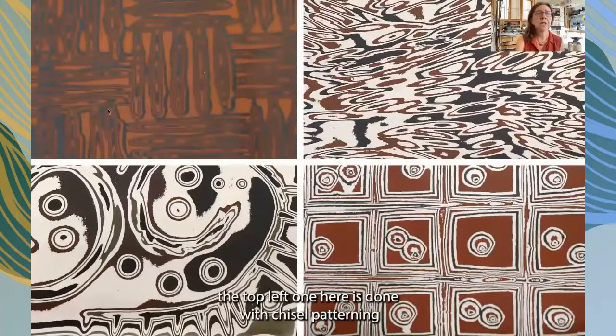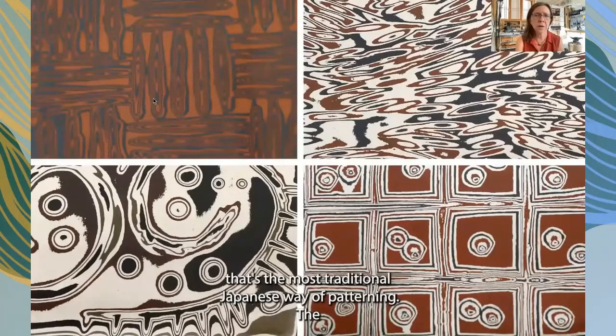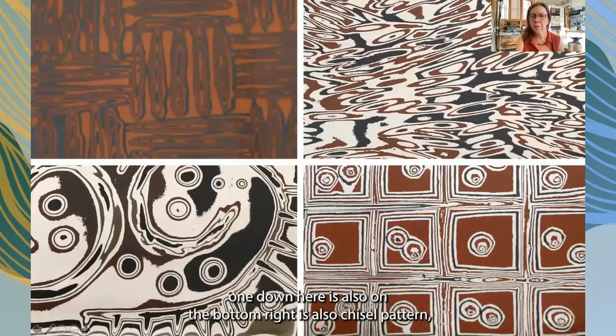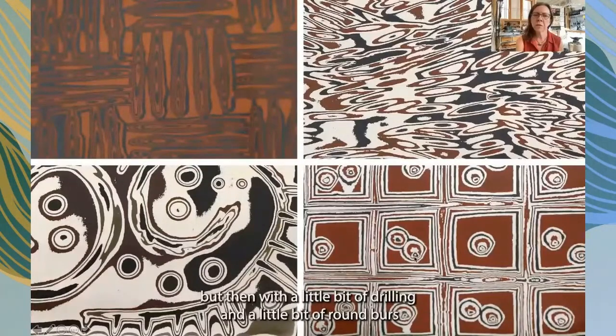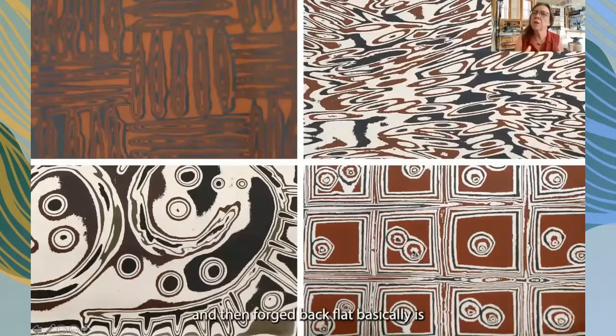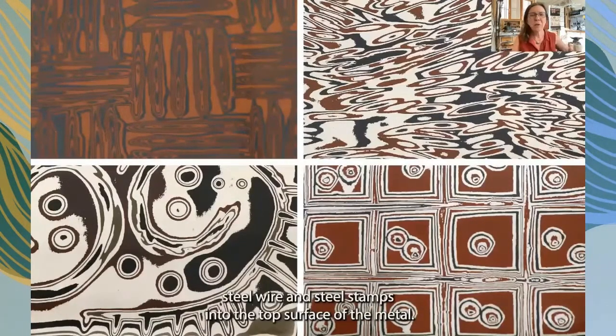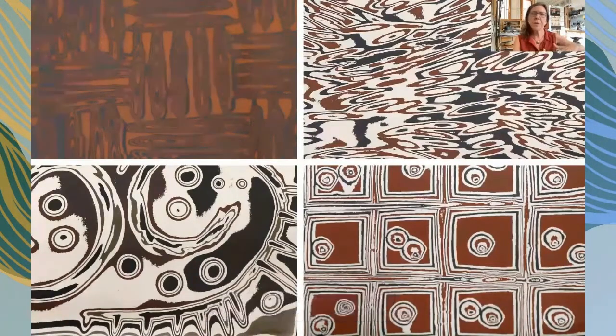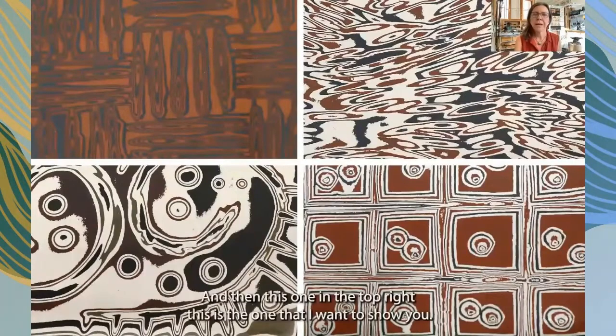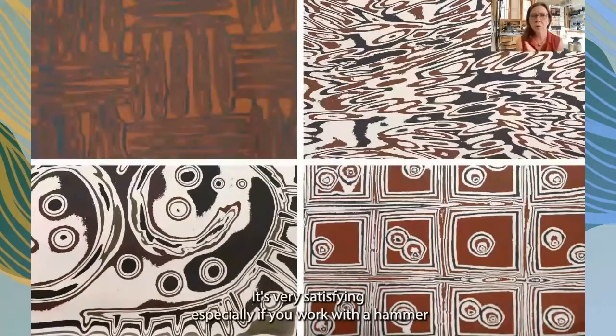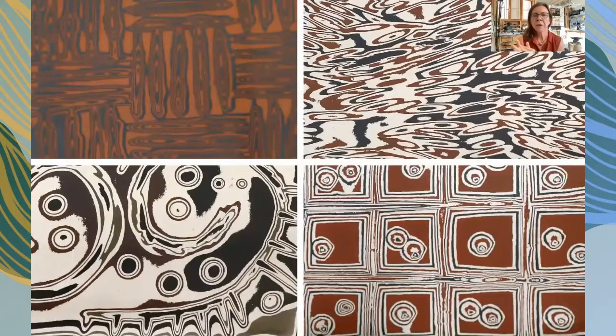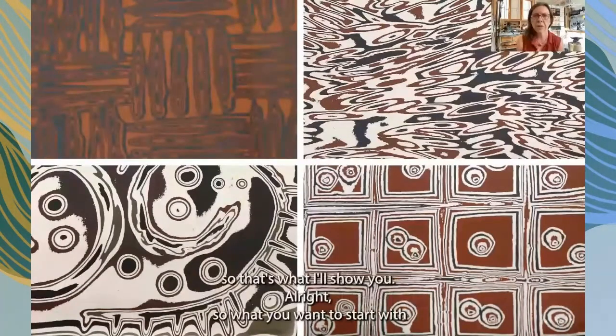The top left one here is done with chisel patterning. That's the most traditional Japanese way of patterning. The one on the bottom right is also chisel patterned, but then with a little bit of drilling and a little bit of round burr, and then forged back flat, basically is how that's done. Bottom left is done by pushing steel wire and steel stamps into the top surface of the metal while I'm on an anvil. And then this one on the top right, this is the one that I want to show you. It's very satisfying, especially if you work with a hammer a lot in your own metals practice, because it's really quick and direct. I call it direct hammer patterning. So that's what I'll show you.